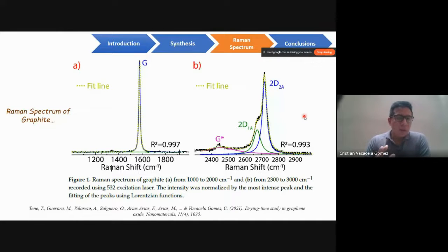If you have a high quality graphite, or your raw material is of high quality, you will see only the G peak, and you will see here the 2D band, or the 2D peak. When you apply the fitting using Lorentzians, the Lorentzian function is widely used to fit the data in Raman spectra. Using these Lorentzian functions, we can identify the contribution of two phonons, as we call them for simplicity.